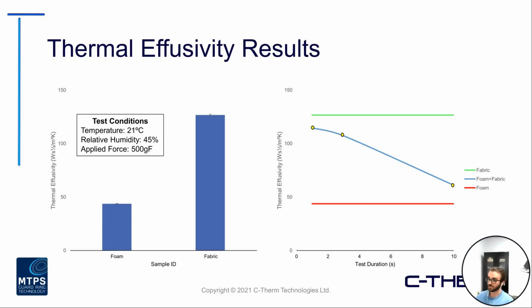So test conditions, again, most of the results that were taken for today's webinar were done at about room temperature, 45% humidity, 500 gram force compression. On the left, you can see just the individual materials model or the measurements that were taken. So the foam coming in just shy of 50 effusivity units, with the fabric being about 125 or so.